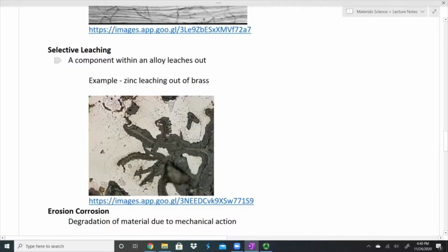We can get selective leaching. We get a component within an alloy that leaches out. So here is an example, zinc leaching out of brass. Brass is a mixture of zinc and copper. And one of them, under certain circumstances, the zinc will want to leave, the copper's fine staying, but the zinc wants to get out of there somehow. And so what it does is it diffuses out and it gets pulled out of my material. Again, what happens is I don't have the same material I used to have because I am losing zinc. So my percentage of copper is going up and my percentage of zinc is going down. I don't have the same material anymore, and I get this corrosive stuff coming out of my material.